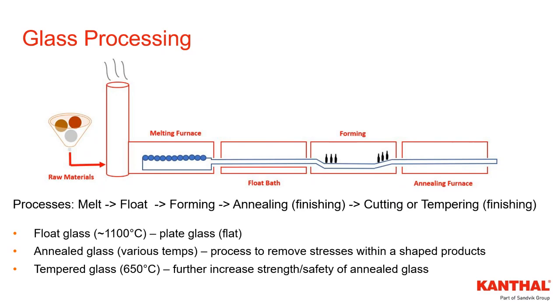Then, more of a forming process is annealing glass. It's done at various temperatures, and it's done to remove any residual stresses from the forming process within a shaped product, for example, a glass bottle. And then another finishing process would be what we consider tempering glass. It's done at 650 degrees centigrade or 1200 Fahrenheit, and it's really done to increase the strength of the glass and to add a safety factor to the glass.